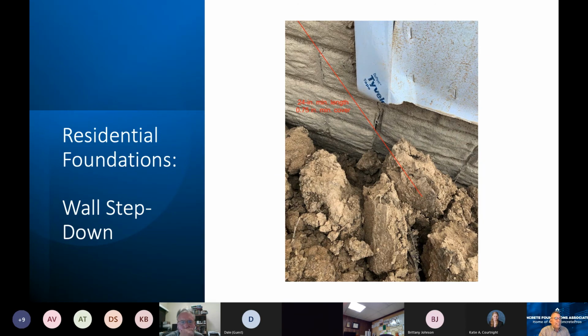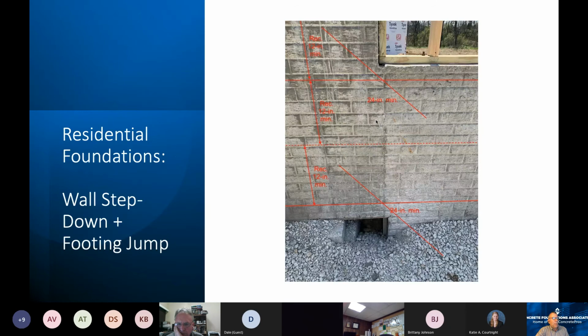Well, it doesn't take a rocket scientist to figure out that somebody's missing what grade line means on the drawing, and they're over it by about 6 inches, because this is just rough grade, and they've still got more to go as they bring in the sod. And so they're getting water pressure down inside their waterproofing, which is back to what I said earlier about how waterproofing fails. This is an example of both a step down and a step footing condition, which is not too common, but it happens a lot on these walkout and daylight townhome conditions.